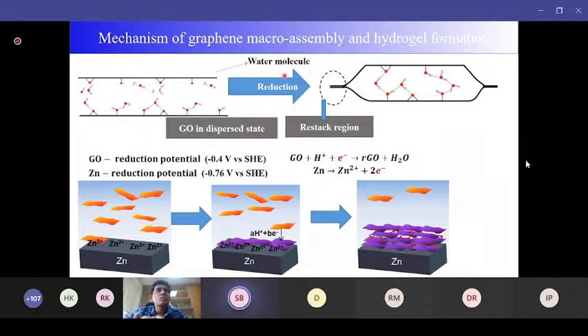Now when you reduce it by some chemical form, what happens? You see that in these regions I have stripped off the functional groups selectively here and here. Once I strip off the functional groups selectively, the graphene sheets have a strong van der Waals interaction. So due to the strong van der Waals interaction, there will be overlapping in this area. However, due to the still presence of some residual functional groups, they make some hydrogen bonding with water molecules, and this water is stably bonded with this particular framework.